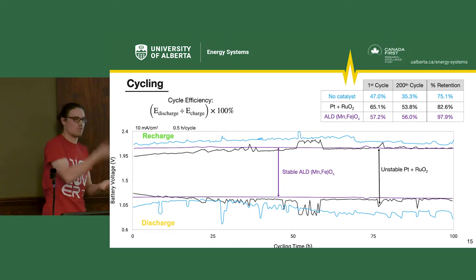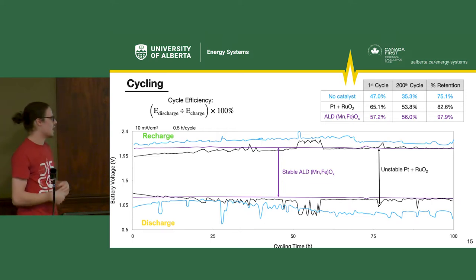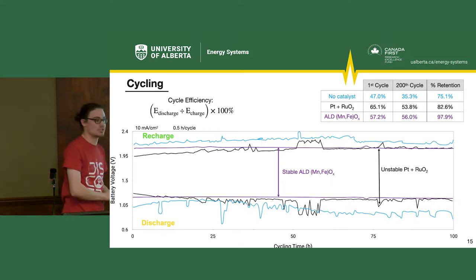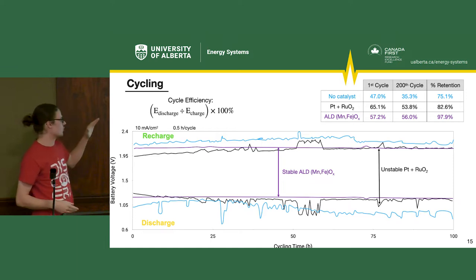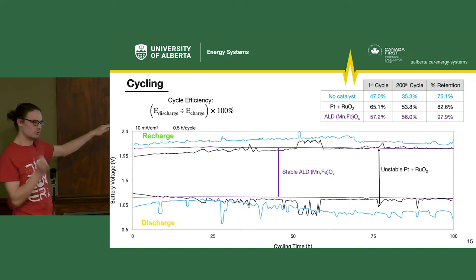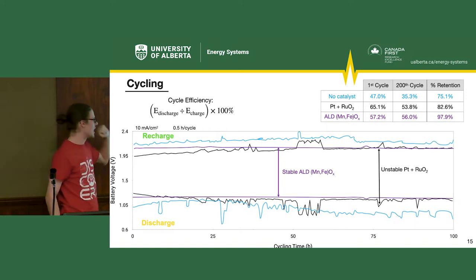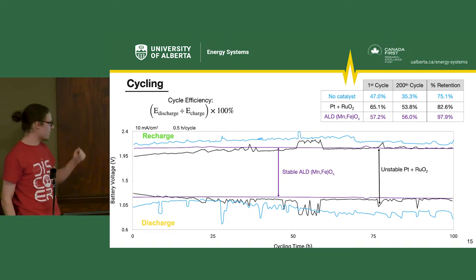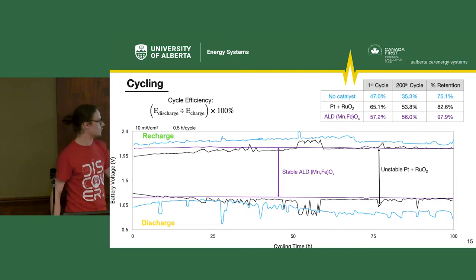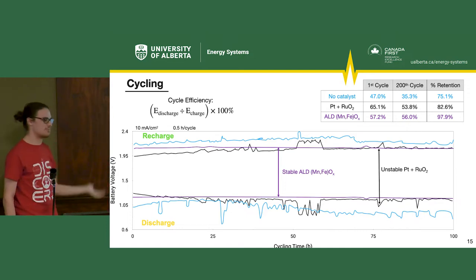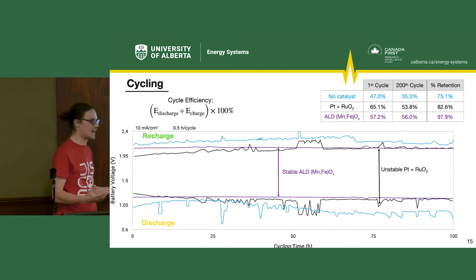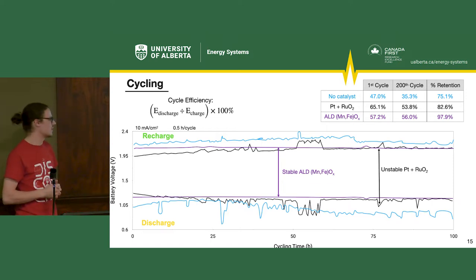Recharge it, discharge it. Do it over and over again, just accelerated testing for 100 hours. So that's 200 cycles in my case. And I compared that for no catalyst in blue, the platinum and ruthenium oxide, the go-to precious metal catalyst, in black, and mine in the purple. And the very first cycle, the very first time I do it, you can see there, platinum, again, is better than my ALD catalyst. We thought that would be the case.